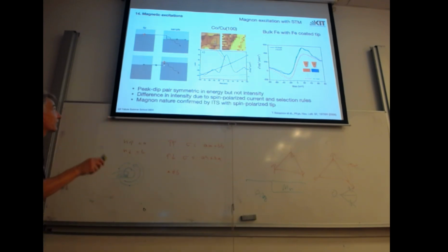And now this is the ordinary ferromagnet, cobalt, and you see 0 bias roughly here, the peak at positive and the dip at negative voltages, and the heights are now very different. Looks like a second derivative here, so this is inelastic spectroscopy. Let's say these are magnons. Why are the intensities different? Because my tunneling current is still polarized. So you remember, this is a non-polarized tip, this is a magnetic tip. My current is the current from minority and from majority, and they are not equal because the density of states of the sample are different. So actually, this and that process don't have the same current.